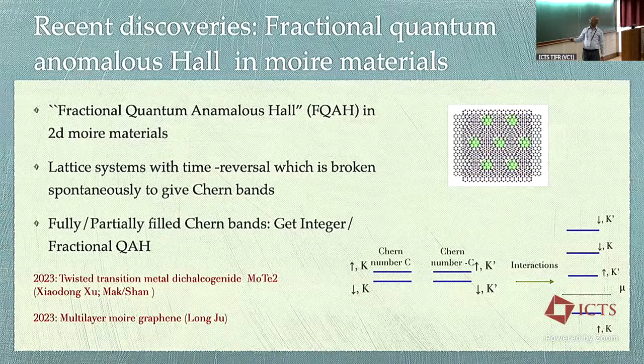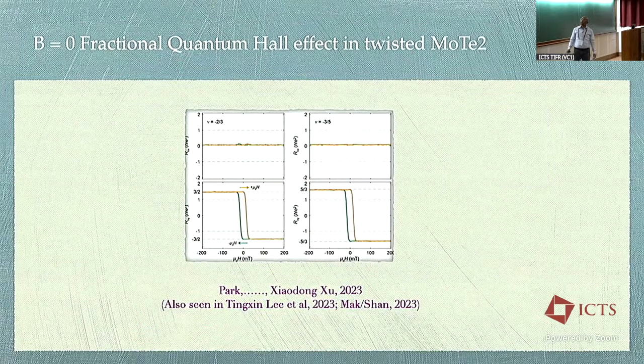Now, if you tune the density so that you only partially fill this Chern band, you might have hoped that you see a fractional quantum Hall effect in zero magnetic field. And that was a hope in the theory literature, but it was realized in experiments 2 years back, first in twisted molybdenum ditelluride, and shortly thereafter in multilayer Moiré graphene, again rhombohedrally stacked, just a few months later. So you have a couple of different systems in which this phenomenon is seen. So let me show you some data.